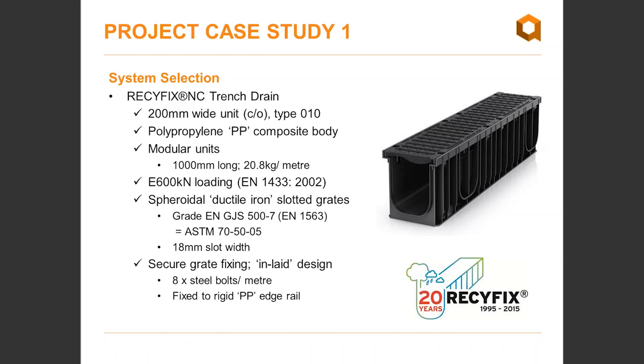Modular units were 1 metre long, and here you can see how light they are, 20.8 kilos, so very, very light units. And the loading was E600, so it's a heavy duty load. The grate was spheroidal ductile iron, slotted grating, and the grade that we supply is equivalent to ASTM 705005. So it's a high grade of ductile iron, and the slot width was 18mm, so again great intake capacity. As Dominic mentioned, this system has a grate with 8 bolts per metre, 4 bolts per half metre grate, and these are fixed into the edge frames for a very durable system.